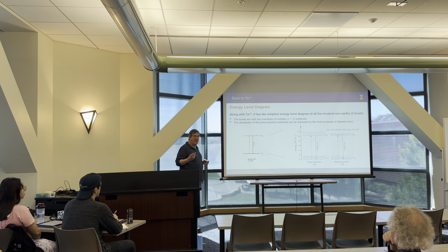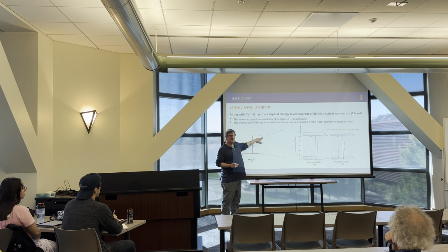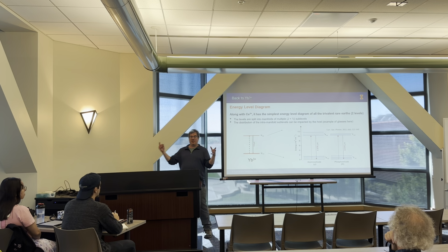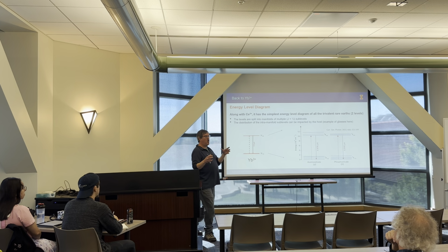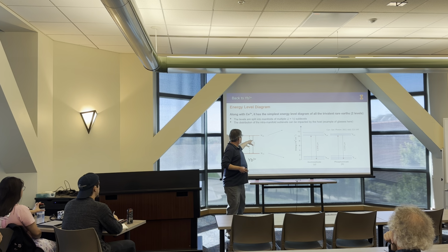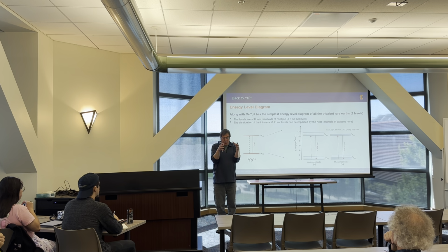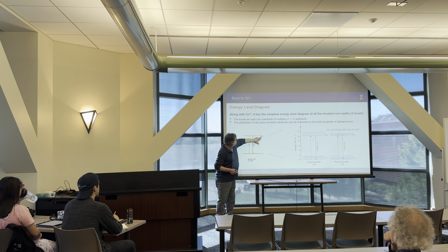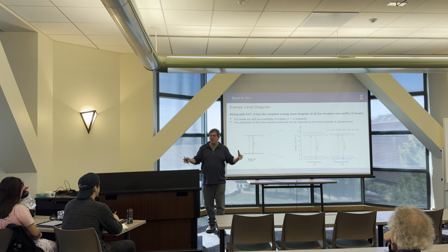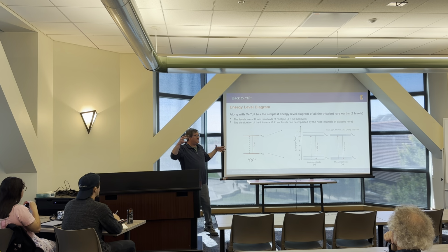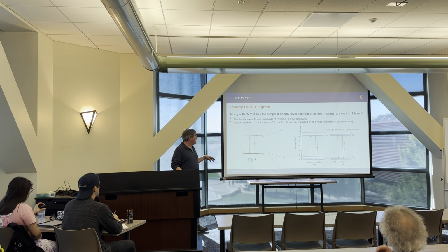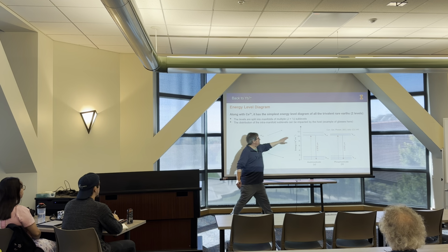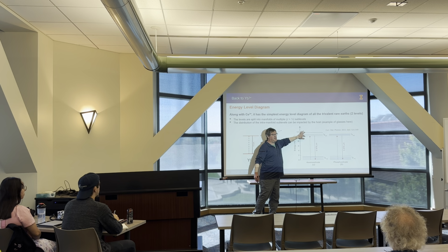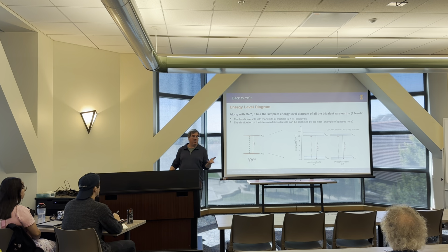Why are they split? Well, the degeneracy here is broken by the host itself. Even though, in a vacuum, for instance, this may have 2 levels that have their own degeneracy, 3 and 4, once you put it in a host, the host and the field that it imparts upon the rare earth will break the degeneracy and split the single level into what we call a manifold. That's Stark splitting. It's an electric field effect.